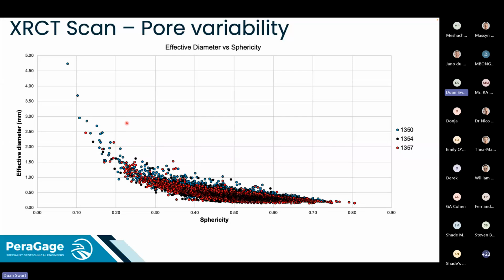Other data you can pull out from the CT scan is sphericity versus effective diameter of each pore. Here are the three samples we looked at. One is the most spherical, essentially a perfect ball, and 0 is not a perfect ball at all. As the effective diameter of the pores increases, the sphericity becomes less. The smaller the pore, the closer it tends to a ball shape. The bigger the pore, the more stretched out it is, which makes sense if you remember the video. Everything is oriented and the pores are quite long, and the secondary fractures are based on the relic rock structure.